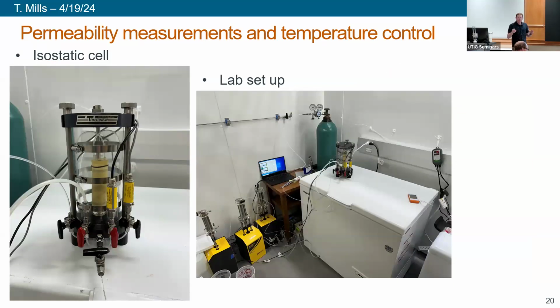Okay, and so once we had those samples, we could measure the permeability of those samples. And so this is how we do that. Over here on the left, we have our sample loaded into this cell. Our sample's here, and it's got some porous stones on top and bottom. And then we can use this bottom port and fill up our cell around our sample with a confining fluid, and then we can pressurize that fluid so that our sample is under the same pressures that it would be out in nature.